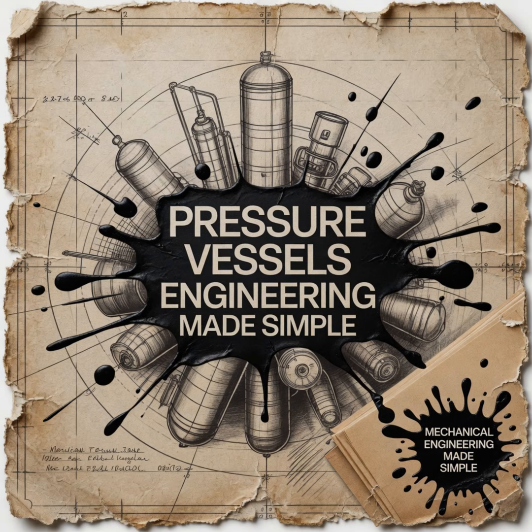They map the nozzle orientations. A massive pipe flange might need to connect to a specific pump on the site. The angle of that nozzle sticking out of the vessel must be within plus or minus 5 millimeters of the CAD drawing. They put straight edges across the flange faces. Why the flange faces? Because if the massive steel flange isn't perfectly flat and parallel to within plus or minus 2 degrees, the bolted gaskets won't crush evenly, and the volatile chemicals will leak out into the plant. And crucially, the inspector uses a flashlight to look for heavy grinding marks. Wait, why are grinding marks dangerous?